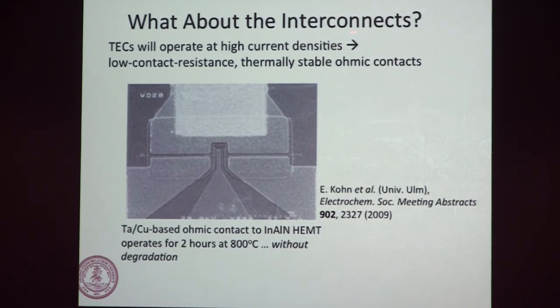In electrical engineering, the thing that's going to fail is always the interconnects. You have issues with interconnects. I ran into some people from France, on their way to a DARPA workshop, who are big on electronics and MEMS at extremely high temperatures for instrumenting gas engines, putting things into the hot zone. And this is an indium aluminum nitride high electron mobility transistor, for you EEs in the audience, operating for a couple of hours at 800 degrees centigrade, where I've often pushed wafers in at 800 degrees centigrade. This thing's operating at 800 degrees, and they've worked on this tantalum copper interconnect, and it doesn't appear any worse for wear for being roasted like that. And this is in the range of the kind of operating temperatures we're going to get to.